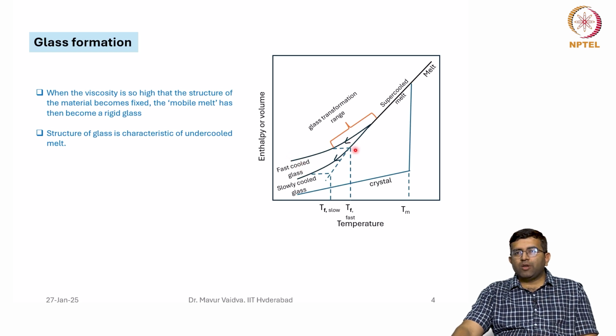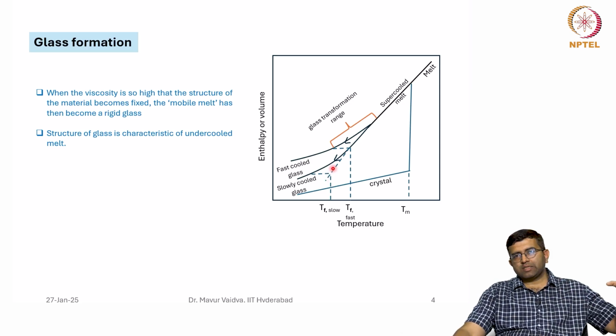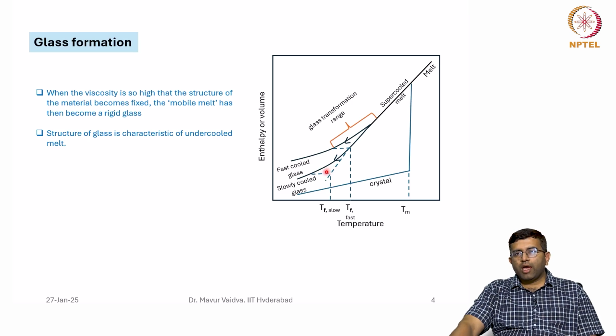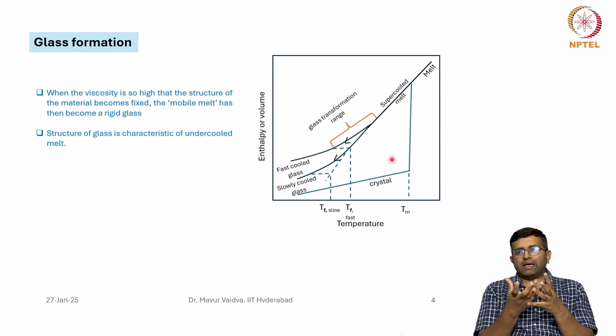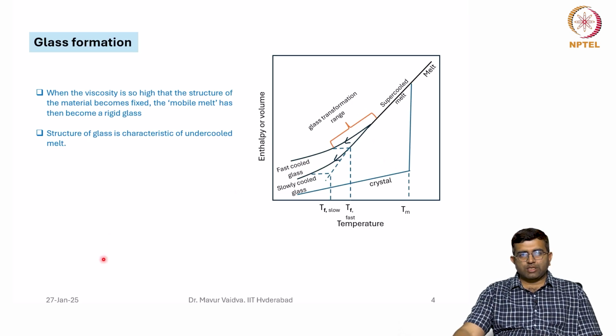This happens below what is known as the fictive temperature, which is derived by this kind of a construction. Now, if you had cooled the glass a little bit slowly, then you would see that the fictive temperature is obtained at a lower temperature. That means the glass formation takes slightly more time to happen. This range, beyond which the supercooled melt gets converted to solid, is known as the glass transformation range. So, the key to form the glass is to avoid this process of crystallization.